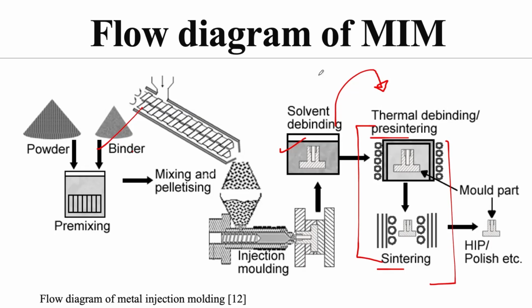Of course, this temperature is not given in one single go. There has to be some cycle which is particularly followed. Once that cycle is followed, the polymer goes away slowly, and the metal powder keeps on fusing together, giving you a final part. This is the overall philosophy, and then you can of course do some post-processing operation after this sintering operation. These post-processing operations can be polishing, or hot isostatic pressing for increasing the density of the parts, so the parts can have more strength. That can be taken care of.